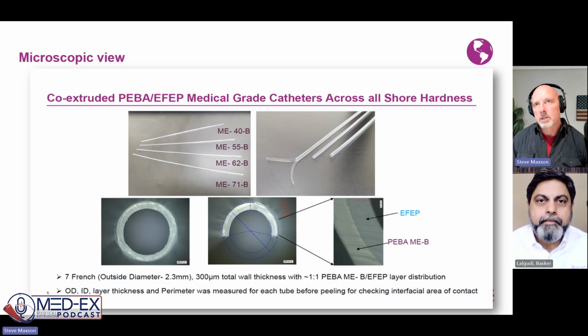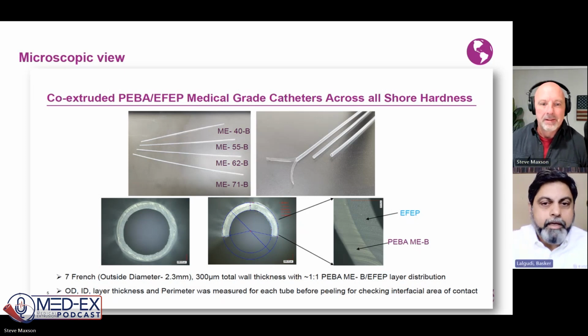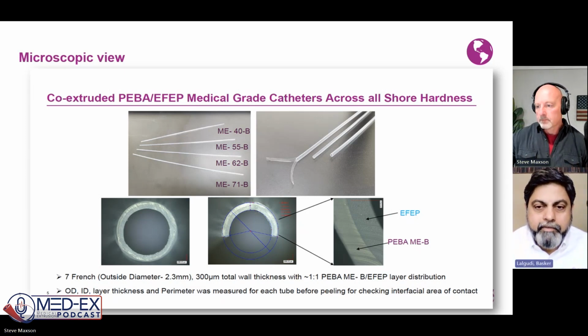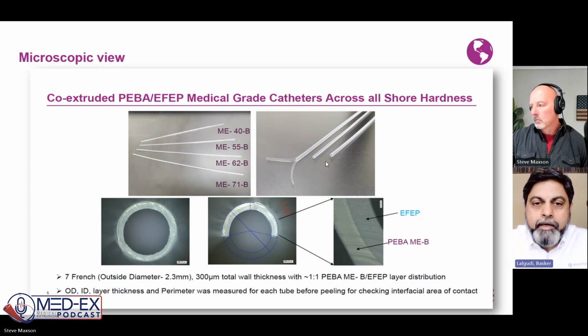Yeah, I think the inner EFEP layer is the one that you really need to thin up, right? Yeah, and there's a very good picture over there. You can see the actual products we made from our dedicated extruder, ME40B all the way up to ME71B. That's 40, 55, 62 and 71 Shore D hardness. On the top right is the actual separation using an Instron machine. You just can't separate them with bare hands. You have to use a machine to separate them.